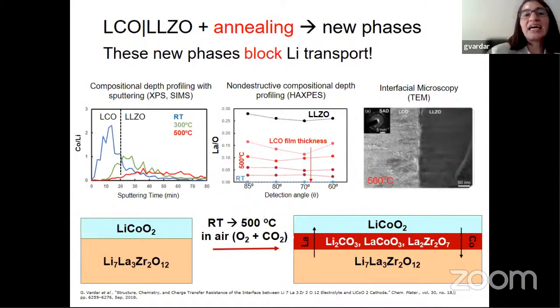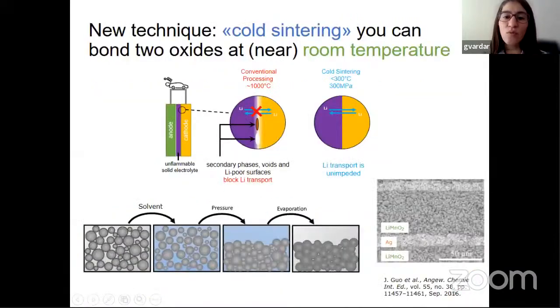Ideally, and we found that basically through my postdoc research, if we put these two materials next to each other, and we try to bond them together by sintering, by heating to high temperatures, there are a lot of secondary phases that form here, like lithium carbonate, lanthanum cobaltite, lanthanum zirconate. These phases form, and they really stop the lithium from crossing over. And so ideally, what we want is this new technique that I'm working on right now in the lab, which is called cold sintering. Cold sintering is different from conventional processing where you heat it up to 1000 degrees. Instead of doing high temperature sintering, we would combine these two materials, this solid electrolyte and this cathode, at around room temperature.